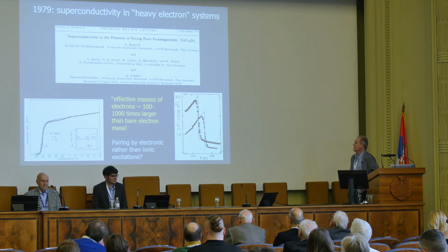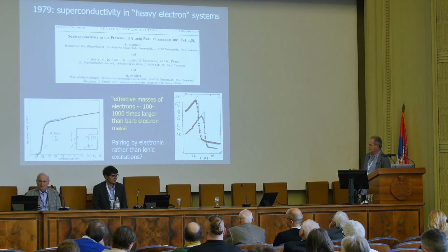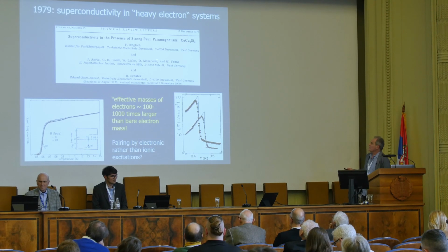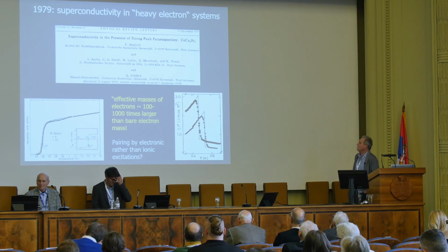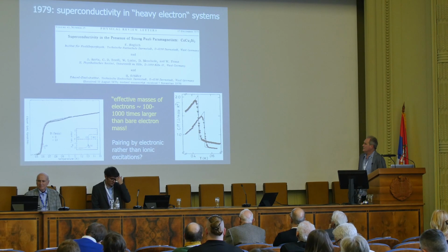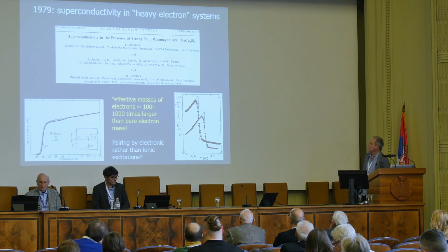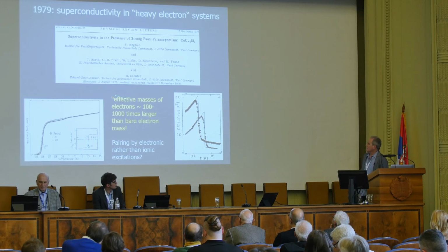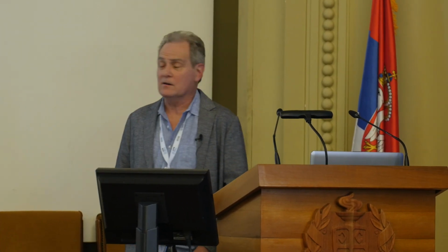The main one is heavy fermions in 1979. Frank Steglich in Darmstadt and his group discovered superconductivity in a material called cerium copper 2 silicon 2. Cerium is a rare earth element which has f electrons. This was new terrain at that time. And of course, the surprising thing was that this had been known already to be a so-called heavy electron material. The effective masses in these compounds were 100 to 1,000 times larger than the bare electron mass.